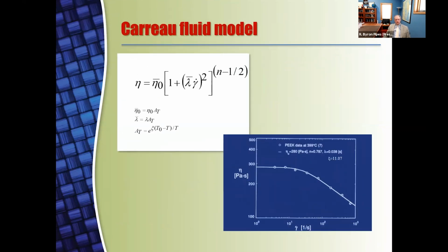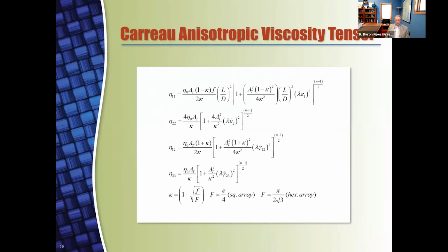These fluids that we work with, when we put particles in them, are no longer Newtonian fluids. They exhibit shear thinning characteristics. They exhibit temperature dependence, of course, that they had long before they were suspensions. And you can take this model with Carreau and represent all of that, the shear thinning, the temperature dependence, and the like, and the recovery of the Newtonian viscosity at zero shear rate. If you do that, you can predict all of the anisotropic viscosities for such a liquid that contains collimated discontinuous fibers of length L and diameter D.